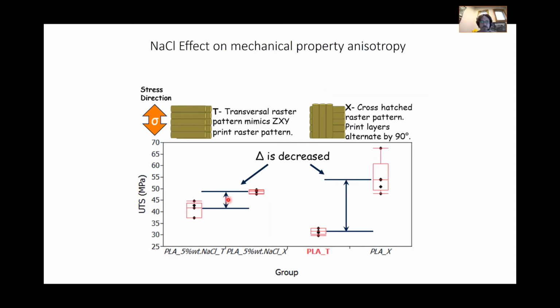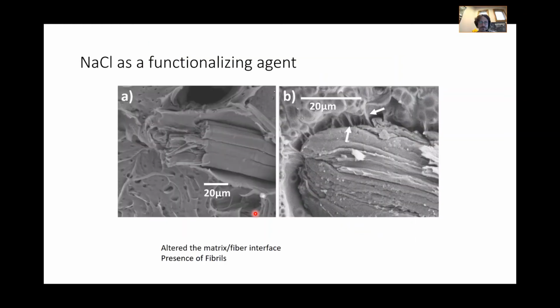We lowered the difference between Z-like printed specimens and something with a different raster pattern. So we decreased raster pattern sensitivity, basically, by adding salt. That was pretty profound - we made a composite that decreased anisotropy. That's pretty cool, especially in the additive world.